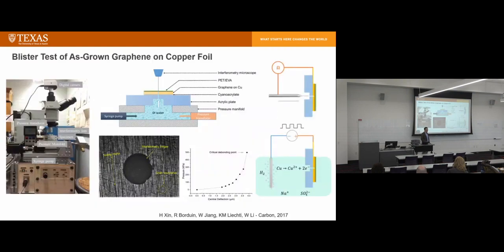So what we need to know, in terms of controlling the process and understanding the peeling behavior, is the adhesive energy between graphene and copper in the as-grown setup, right? After you grow graphene on copper, what is the adhesive energy between as-grown graphene and copper? So we use the same blister test setup.